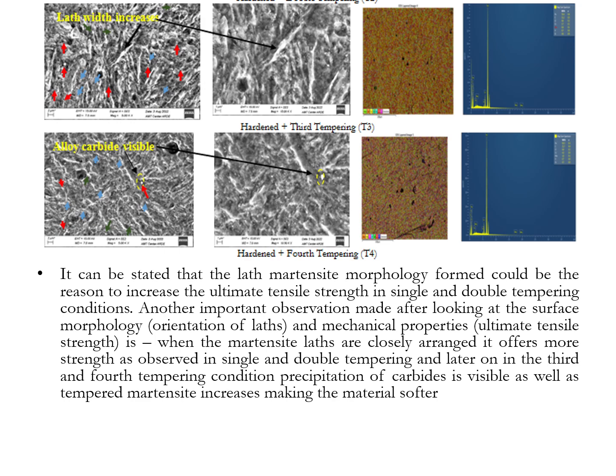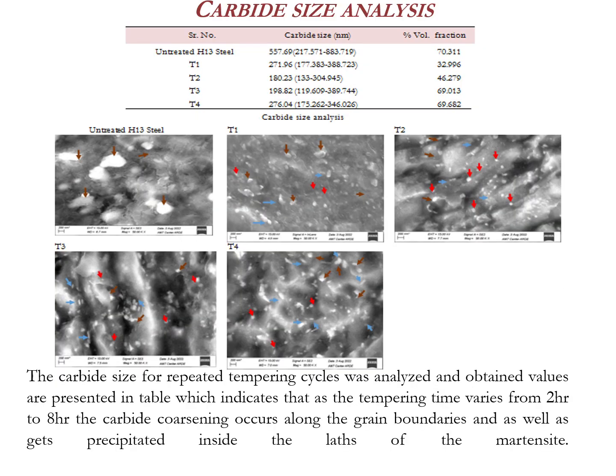Another important observation made after looking at the surface morphology, that is orientation of laths and mechanical properties, that is ultimate tensile strength, is when the martensite laths are closely arranged, it offers more strength as observed in single and double tempering condition, and later on in third and fourth time tempering condition, precipitation of carbides is visible as well as tempered martensite increases, making the material softer.